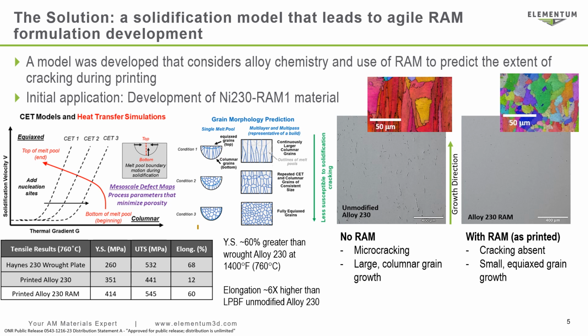We were able to predict and fix the cracking problem by investigating the solidification behavior of these nickel alloys. Most cracking in metal 3D printing has to do with what happens when the molten metal cools. Solidification models give us an idea, based on the composition and cooling conditions, to which formulations favor a grain structure that avoids cracking. On the left, we have a RAM-free printed alloy 230 showing fairly large vertically oriented columnar grains in this colorful grain map that you see. Underneath that, we see cracking in the microscope image. When RAM is added, the cracking is eliminated, and the grain map on the right shows the smaller, rounder grains that are randomly oriented. The table below illustrates the consequences of the RAM additions at the microscale.